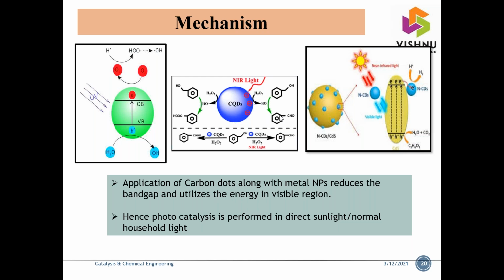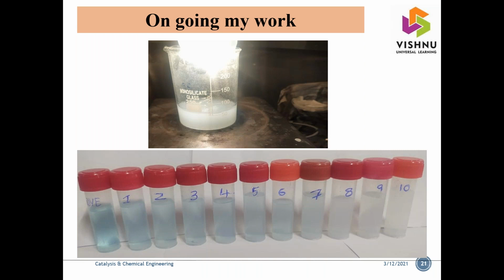so those can create the holes, oxygen radicals and hydrogen radicals. Those will degrade the pollutants. Here is our ongoing experiment. We are using titanium oxide carbon nanocomposites. We also observed the degradation, though we are not showing much detail of the results here.